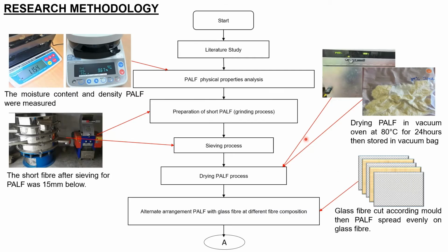Here is the methodology. After we finished the literature review, we did the PALF physical properties analysis. Here we measure the moisture content and density. Then comes the preparation of short PALF, which is a grinding process using this machine. And then we sieve the PALF using a sieve machine, and the output of short fiber is 15 millimeter and below.